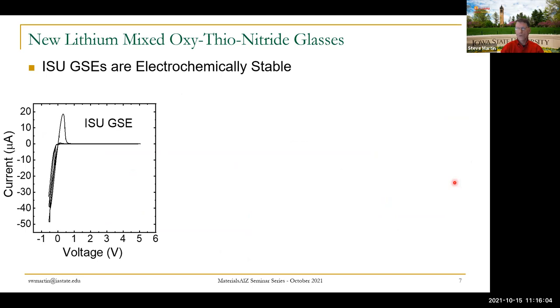Further, however, there's a whole suite of electrochemical properties that glass must be able to possess. And again, one of which is stability, electrochemical stability. They have to be stable at 0 volts because we're going to use lithium metal as the anode. Lithium metal is a very strong reducing agent. There can't be any reductive reactions at the anode other than, as you see here, what are called plating and stripping. The lithium ion coming off of the glass into the electrode, or coming off of the electrode and into the glass. That's the primary charge transfer process. And that's what's shown here. We're plating out with positive currents and stripping with negative currents. And then we pull on that voltammetrically out to about 5 volts.